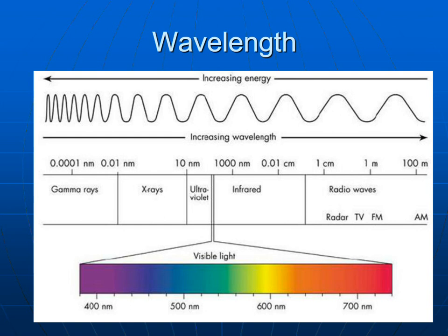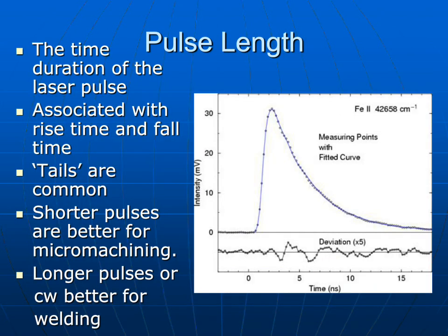Lasers also have a defined pulse length, especially those lasers that are used for machining or material removal applications. The pulse length is the time duration of the laser pulse. With that time duration is associated a rise time and a fall time. The rise time is usually fairly rapid, and the fall time is usually indicative of some sort of a tail, so you have a slower fall time in most cases. As a general statement, shorter pulses are better for micromachining, and as a general statement, longer pulses, or CW, are better for welding.